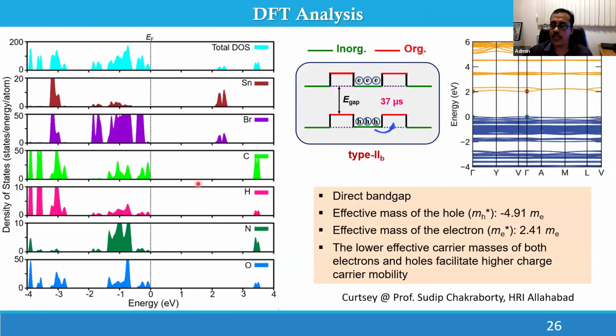And here we did the analysis, and here the inorganic component is contributing to the conduction band minimum, and the organic component contributing to the valence band maximum. That is type 2B band alignment, and we did the detailed band structure analysis and understood the effective mass of the hole, that is minus 4.91 me, and the effective mass of the electron, that is 2.41. It is comparable, and both the electrons and holes contribute to higher charge carrier mobility in this system.